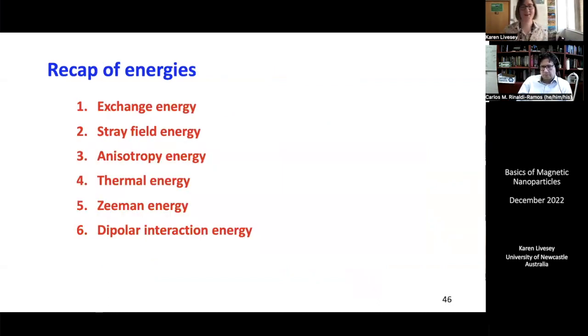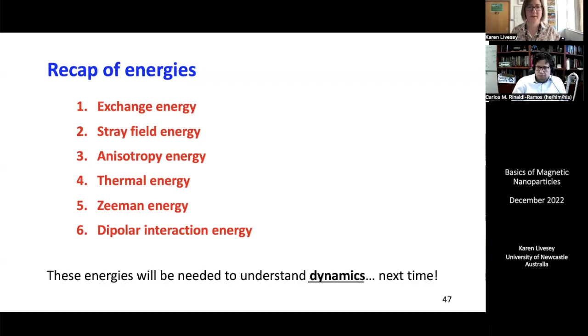Okay, so we have done 6 different energy contributions of a magnetic nanoparticle, and we will use some of these in the coming lectures. We've done exchange energy, stray field energy, anisotropy, thermal effects, Zeeman energy, or the interaction with an external applied field, and dipolar interaction energy, which I think is the most complicated.